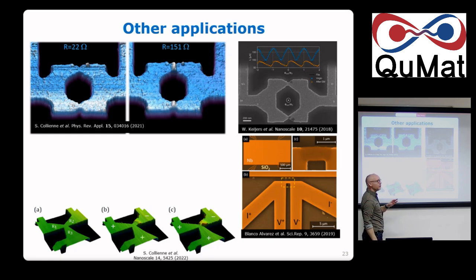This is niobium, so it's a bit tricky. It's not just constriction. It's also oxidation, local oxidation, because it's made in air. So you change the properties and you make the weak link weaker. That's what you want.